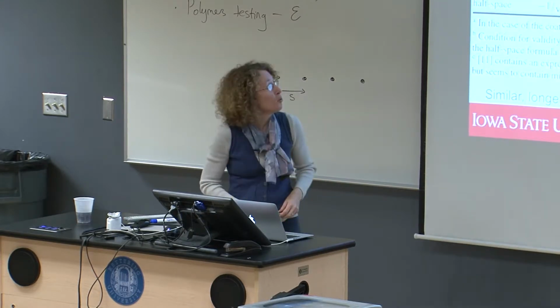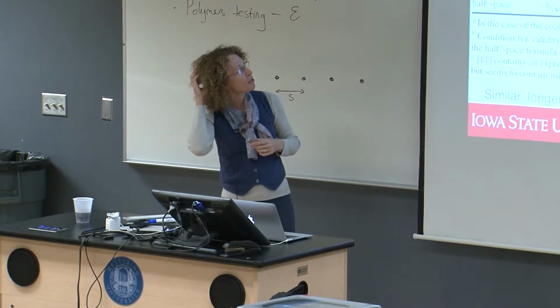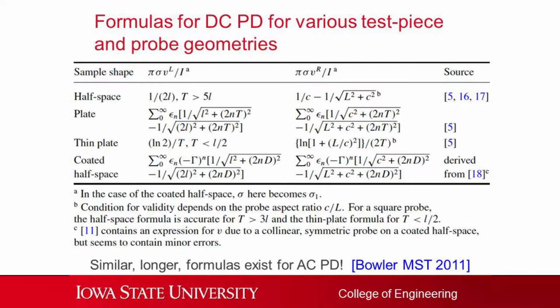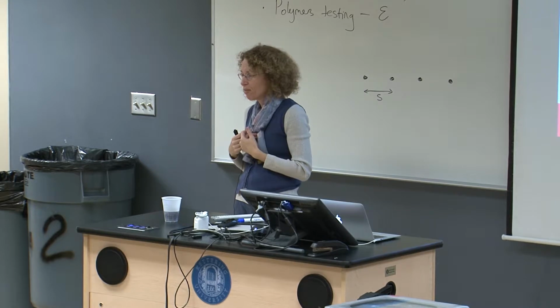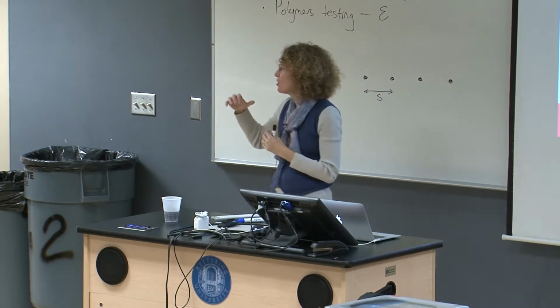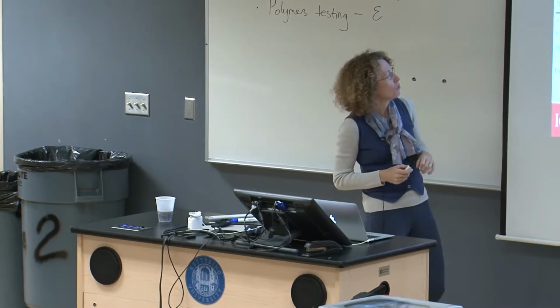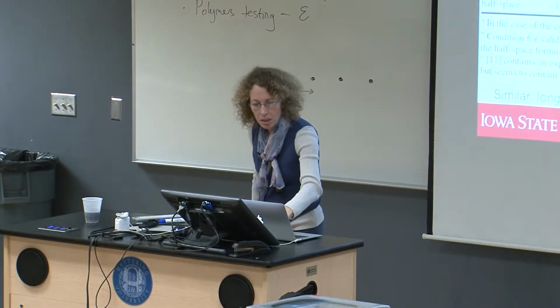If you want to know some different formulas for different shapes of materials, we worked out quite a lot of those. So the shapes are here. If you have a half space, that's the simplest case. A very deep plate would approximate that. If you have a thinner plate, you have a different kind of formula. If you have a coated half space, you have a different formula again. And if we were to look at a cylinder, which has a nice application in the auto industry, in fact, there's still no really good non-destructive way to measure the depth of a hardened layer on a crankshaft, which people would like to have. Then we would have different formulas as well, which are actually pretty difficult to work out.